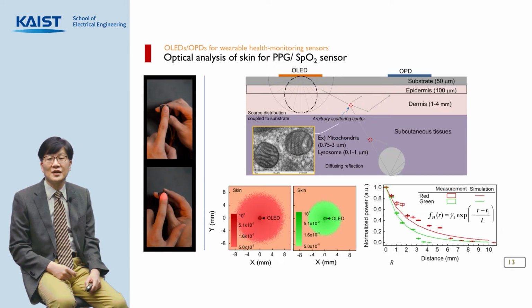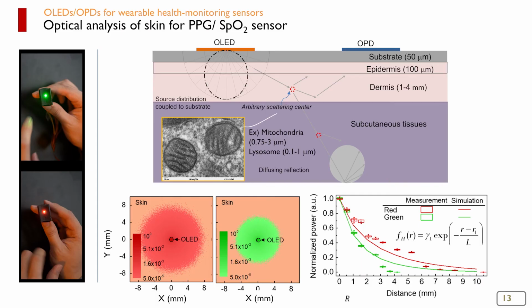To better understand and design an efficient SpO2 sensor, we have carried out an optical simulation for light propagation inside the human skin. It does indicate that light propagates in all directions through scattering from many organelles like mitochondria and lysosomes, which have a sphere-like shape on the order of micrometer scale, and thus can be simulated approximately as Mie scatterers. One more thing to note is the lateral propagation length. You can see that red light spreads wider than green light, and this is due to the fact that human skin has lower absorption in the long wavelength range than in the short wavelength range.